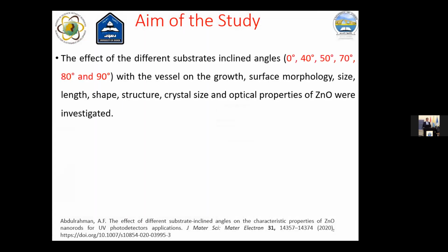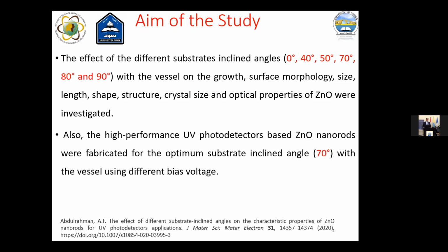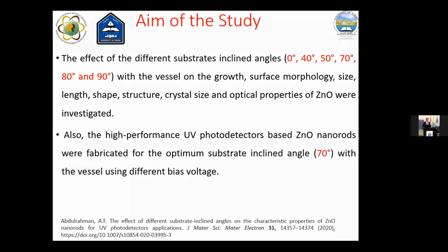The aim of the study: first, the effect of different substrate inclined angles in a wide range from 0 to 90 degrees, with the vessel on the growth and surface morphology, size, length, shape, structure, crystal size, and optical properties of zinc oxide nanorods. Also, a high-performance UV photodetector based on zinc oxide nanorods was fabricated for the optimum substrate inclined angle at 70 degrees, using different bias voltages.